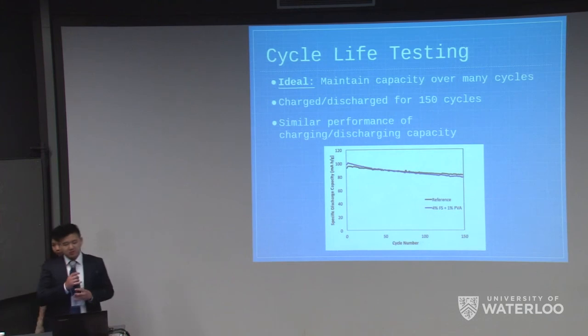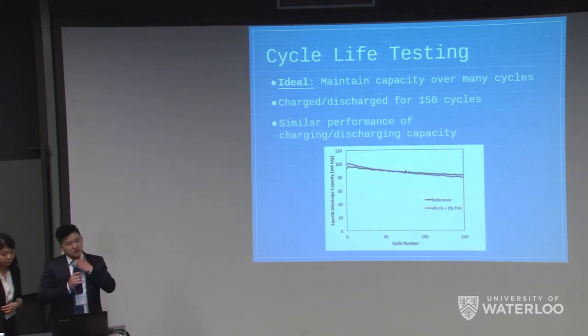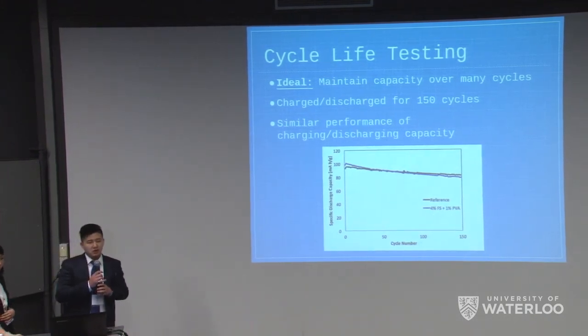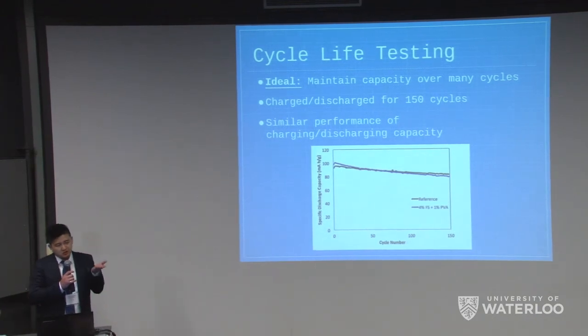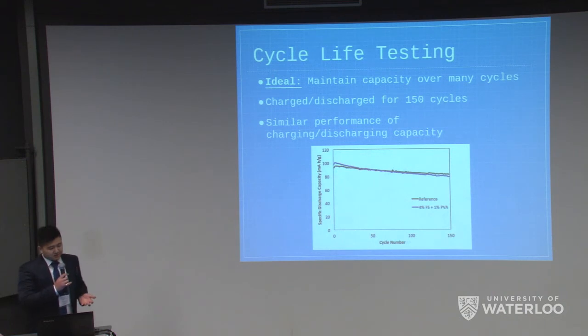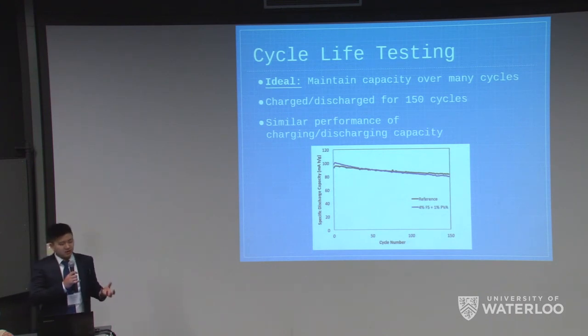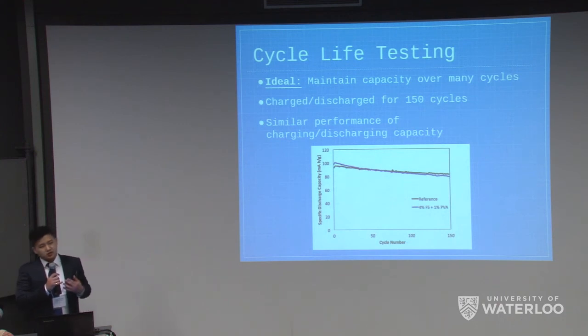Another test that we performed is the cycle life test. Because it's a rechargeable battery, ideally we want it to charge up to the same capacity, but obviously it doesn't in reality. And so we had to run some cycle life tests using the electrolyte in a battery system. Each cycle was charged at the rate of 1 C, so that it takes an hour to charge, and then discharged at 1 C as well.